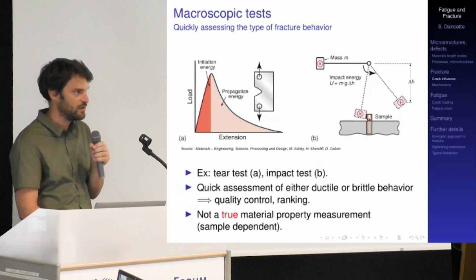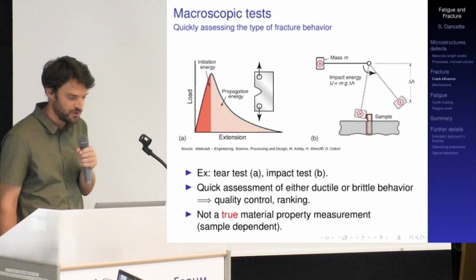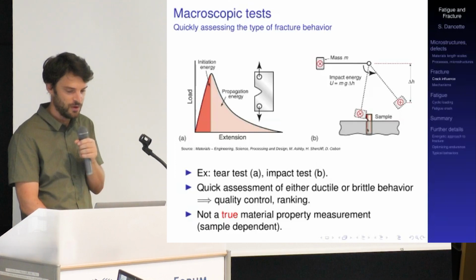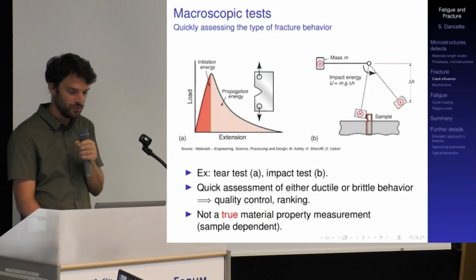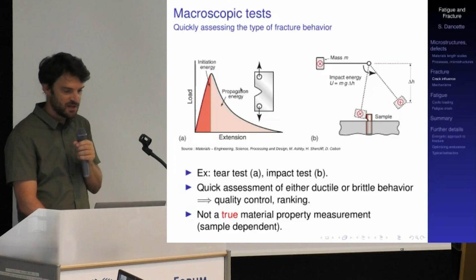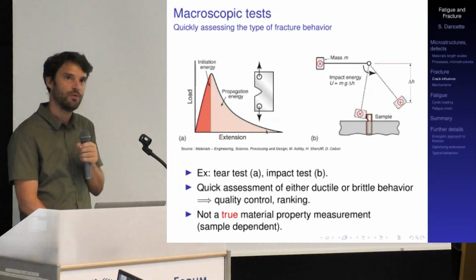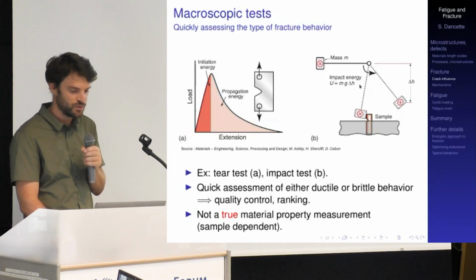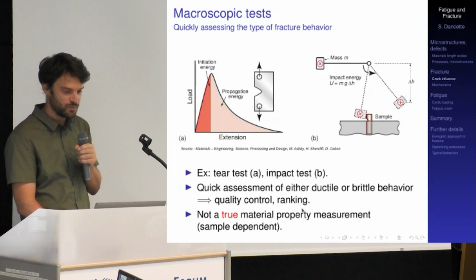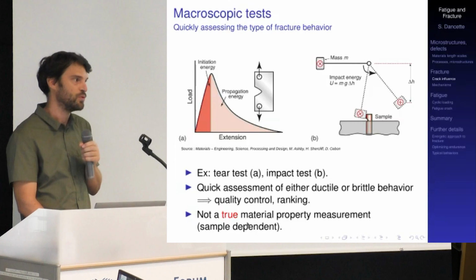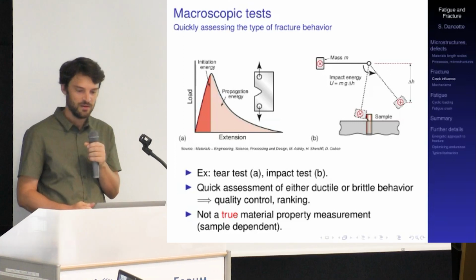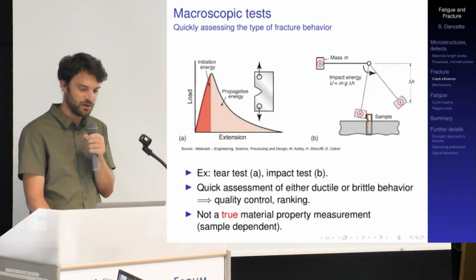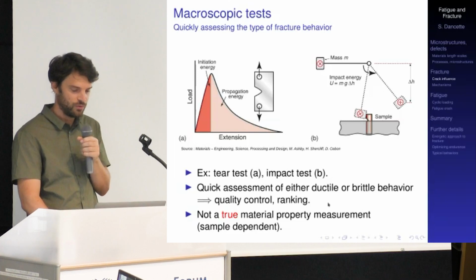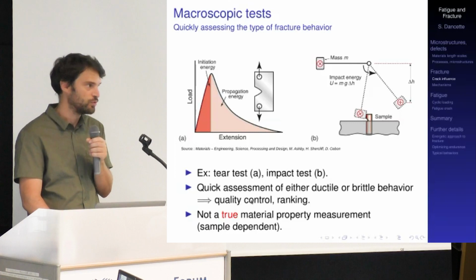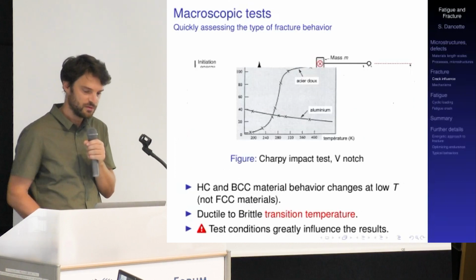That version would be the ISO test, and you can also easily find the Charpy impact test, which would be rather a case of three-point bending. So the problem with these tests is that they are relatively easy to perform, and it is relatively easy to measure some kind of fracture energy out of this, but this is not really a true material property, because all of these ways of measuring fracture depend on the sample size, sample dimensions, shape of the crack, etc. So these are not intrinsic material properties. These tests are useful for quality ranking and quality control, but not for measuring intrinsic material properties.